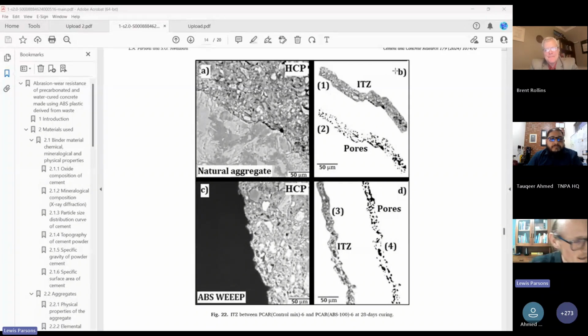So if this is true, and we have this colloidal silica that you're proposing, I think that since it is that small and it can create nucleation sites, and since the interfacial zone is generally more porous than the rest of the bulk paste, you will most likely find additional, or let's call them secondary, calcium silicate hydrate gel formed between the bulk paste, refining the interfacial zone. So I would expect that using this colloidal silica will result in perhaps a more refined ITZ. And obviously, if you have a more refined interfacial transition zone, you can expect improved durability and most likely strength.